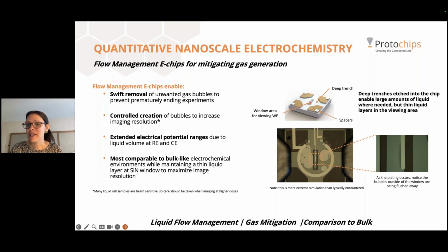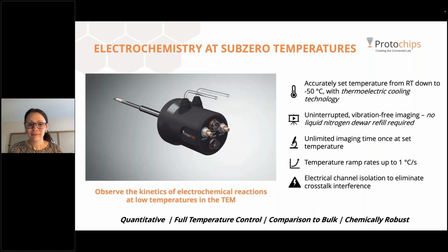This is to keep your imaging area, the liquid in that area, thin, but we've had thicker liquid around, which will help flush the bubbles out much more readily as we flow, and it will also keep a more bulk-like electrochemical environment around your reference and counter electrodes, again, helping to emphasize signal to noise.